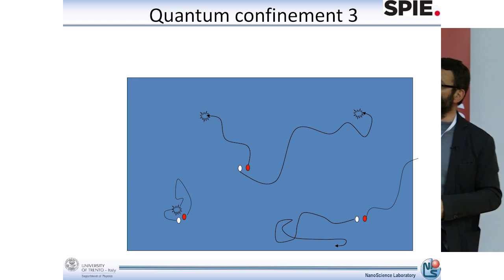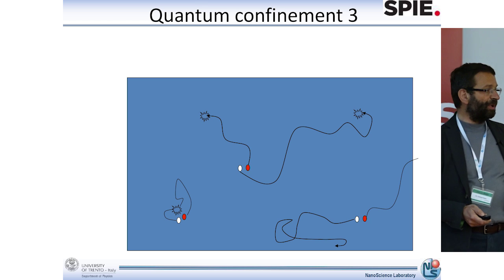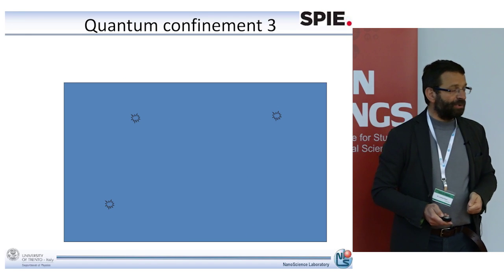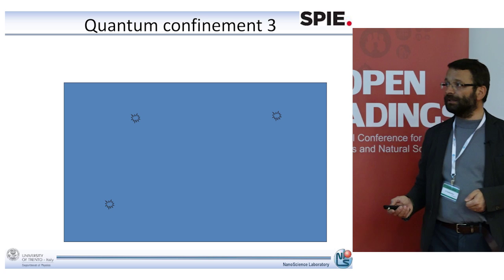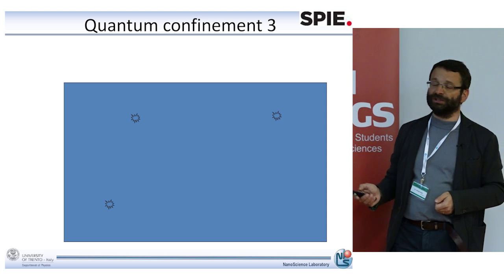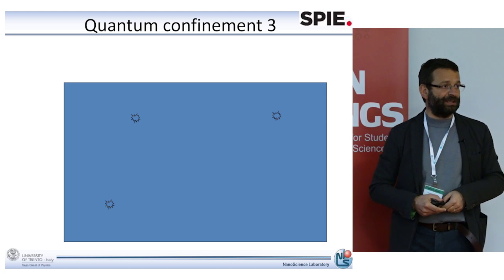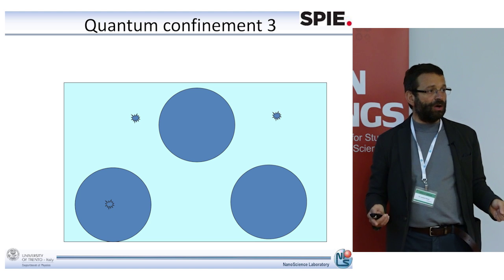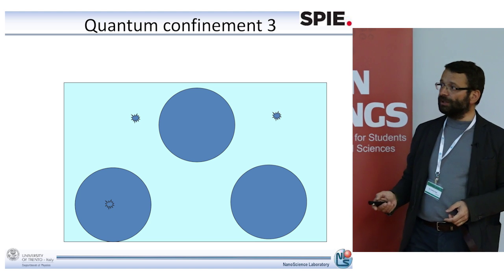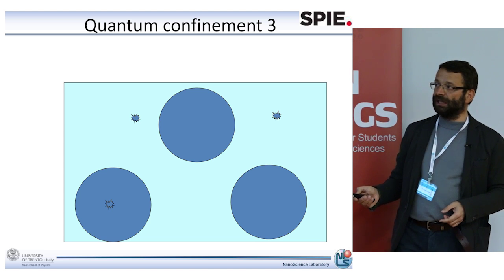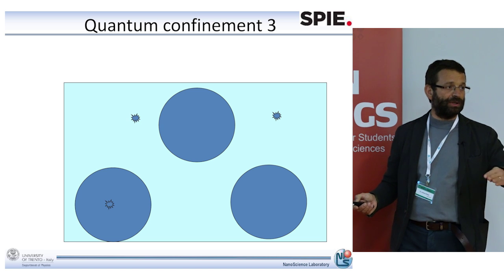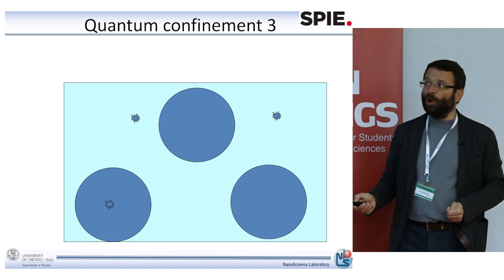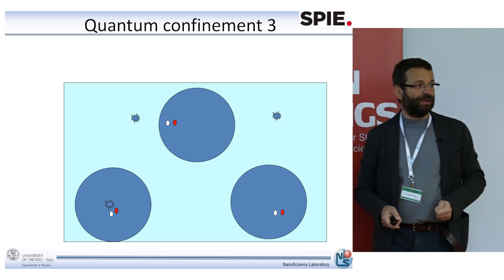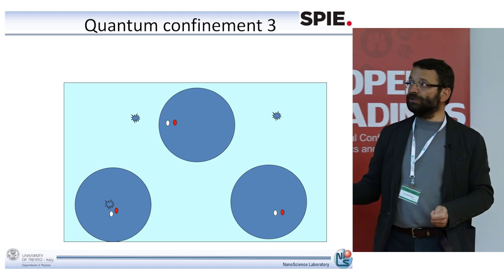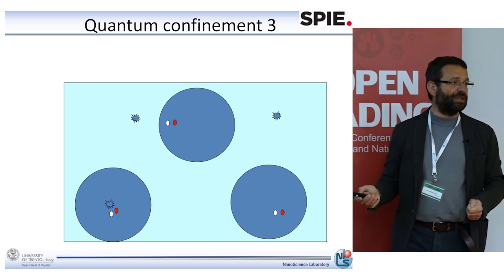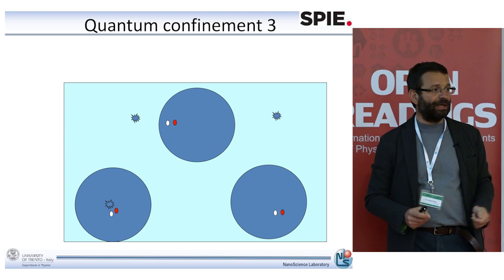And this does not happen for electron-hole pairs in silicon nanocrystals, because now you do excite electron-hole pairs, but they are confined in space. So they are no longer able to move. So either you get one defect in the nanocrystal, and the nanocrystal is completely dark, or you don't get a defect in the nanocrystal. And since you do not have defects, they stay there and wait to recombine radiatively.